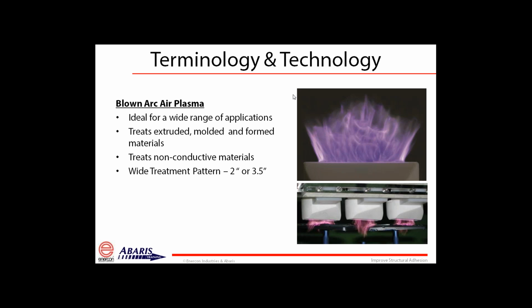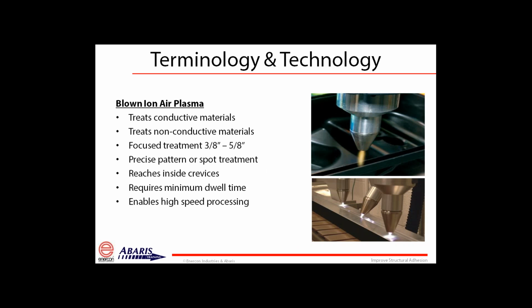The second technology that I want to talk about is what's known as blown ion air plasma technology. This is a very flexible technology that now allows us to treat both conductive and non-conductive materials. The treatment width is a little bit different than blown arc. What we're doing with this technology is we're actually generating that plasma inside of the treatment head itself and blowing out the resulting ions that are produced in that process.